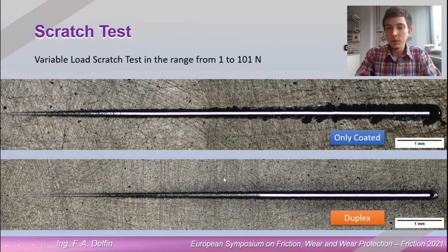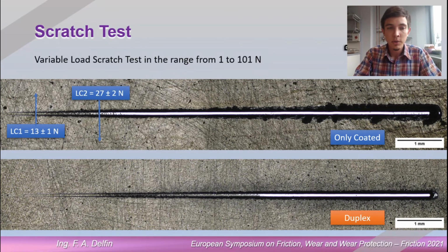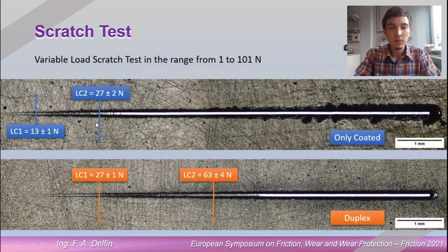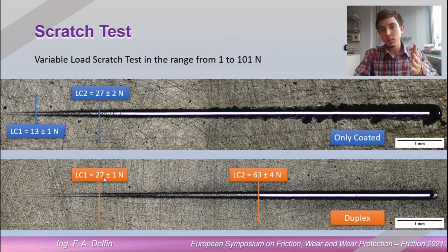And here to prove the adhesion, we did the scratch test, a variable load scratch test from 1 to 101 Newton. And we see the start of the cracking at 13 Newton in the only coated sample, and at 27 Newton, a full delamination in the only coated sample. But for the duplex sample at 27 Newton, it's just the beginning of the first cracking, and 63 Newtons for the full delamination. So this is because of the nitride layer. It helps to dissipate the load we have